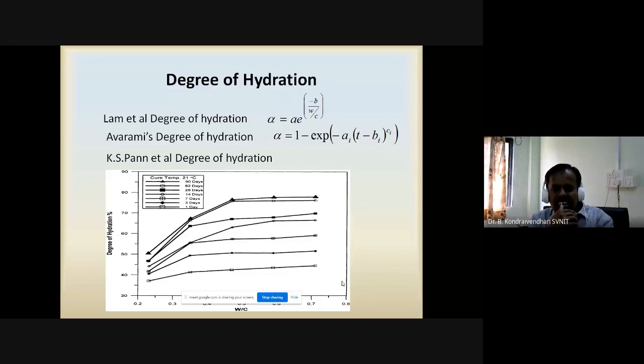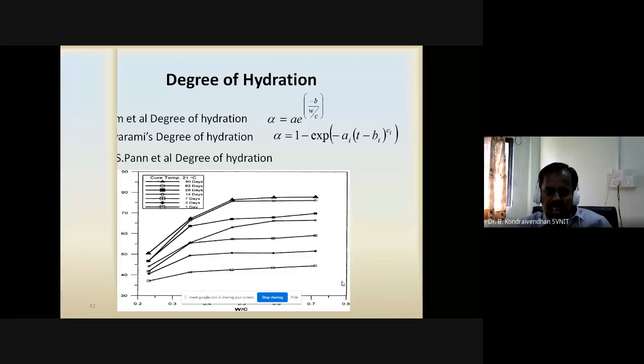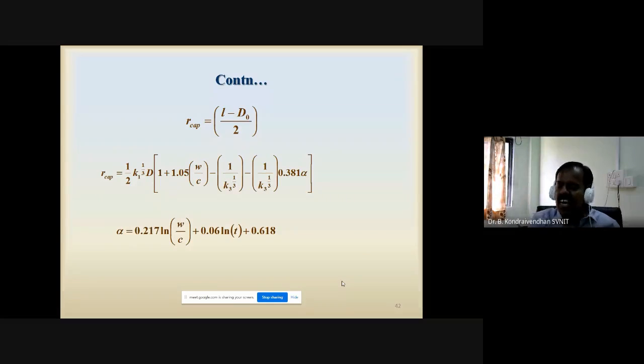Then we have seen there is K.S. Pann et al. He has given the degree of hydration versus water cement ratio for different curing ages. He has given a plot, but it is somehow matching with our intention. So we have taken the K.S. Pann et al. degree of hydration, extrapolated the data and done some multiple regression analysis. That's how we got this previous equation, the degree of hydration as a function of water cement ratio and curing age.